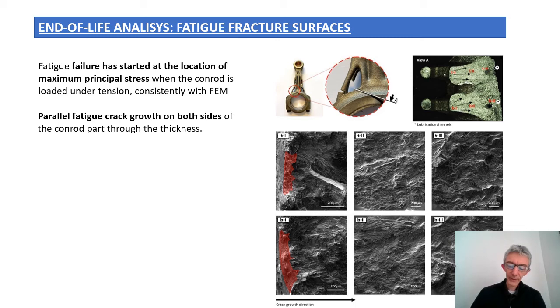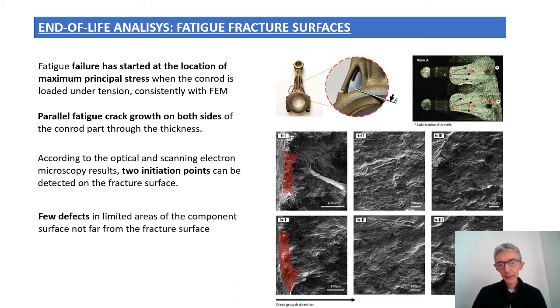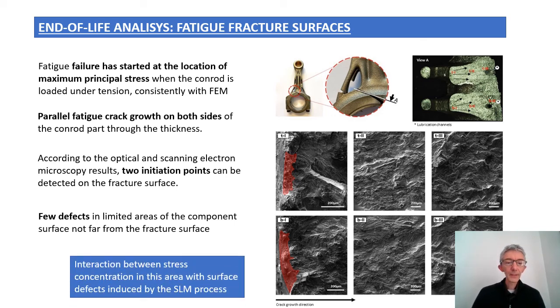The failure initiation was identified on the fracture surfaces, and a parallel fatigue crack growth on both sides of the conrod was observed. In this area, some investigation on the presence of defects was also carried out. So a few defects were found in limited areas of the component surface, not far from the fracture surface, although in general the quality of the conrod was very, very good. So the conclusion is that the interaction between stress concentration in this area and the presence of some surface defects induced by the SLM process actually may explain the failure of the conrod.